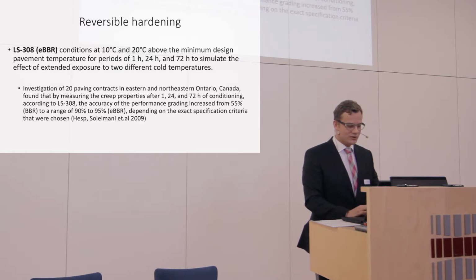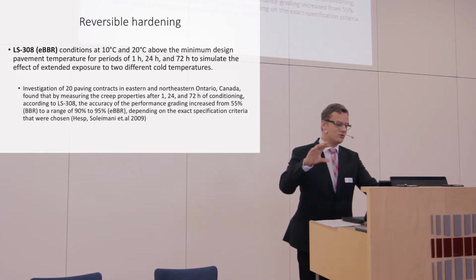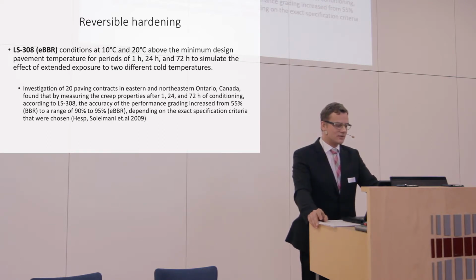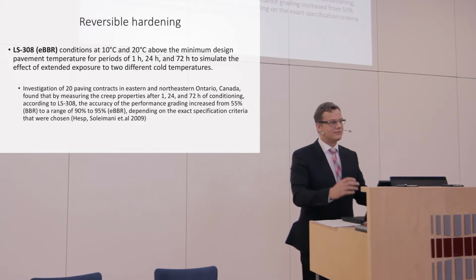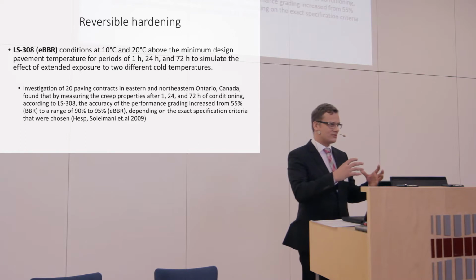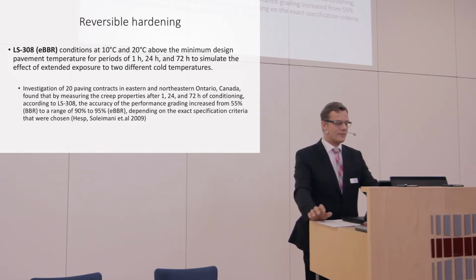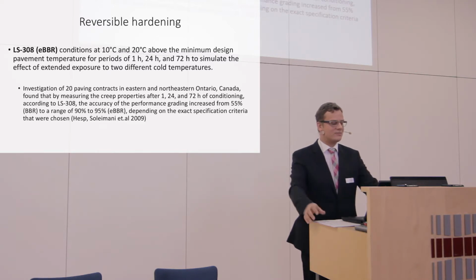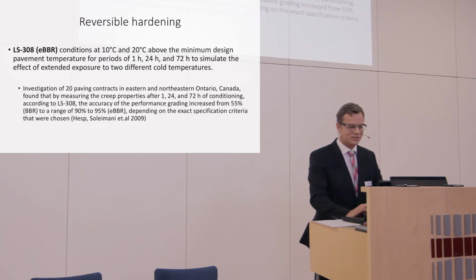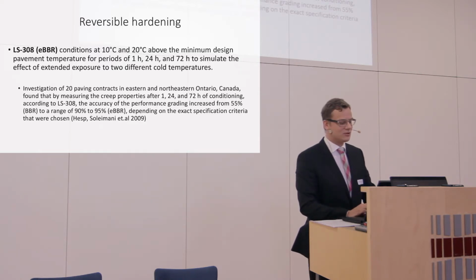An investigation of 20 paving contracts in eastern and northeastern Ontario, Canada, found that by measuring the creep properties after 1, 24, and 72 hours of conditioning in eBBR, the accuracy of the performance grading increased from 50 to 55% for normal PBR, to a range of 80 to 85%, well, 90 to 95% for eBBR, depending on the exact specification criteria that were chosen.